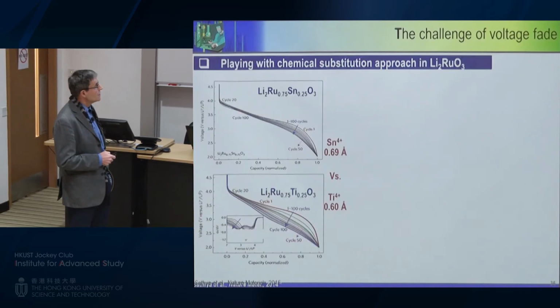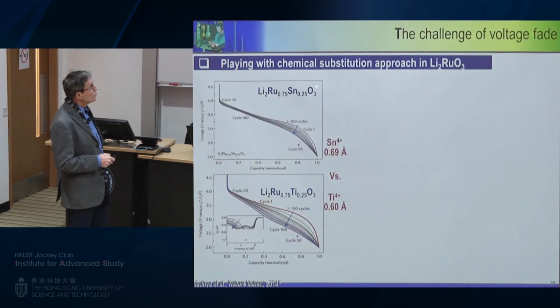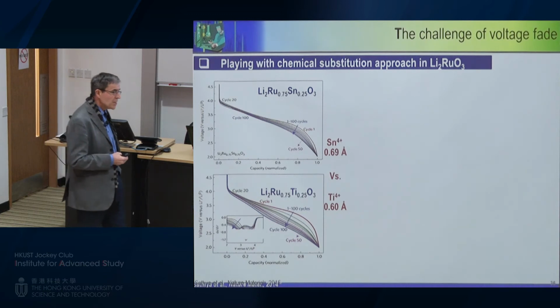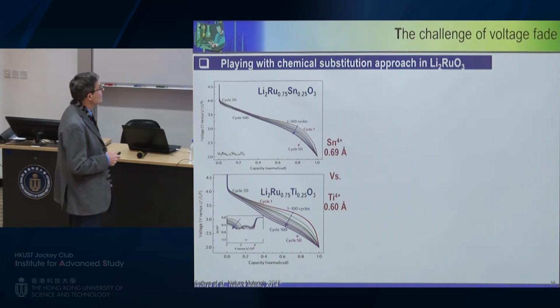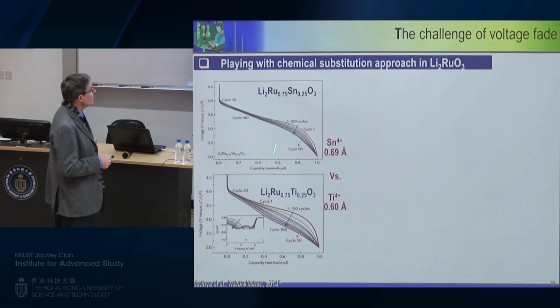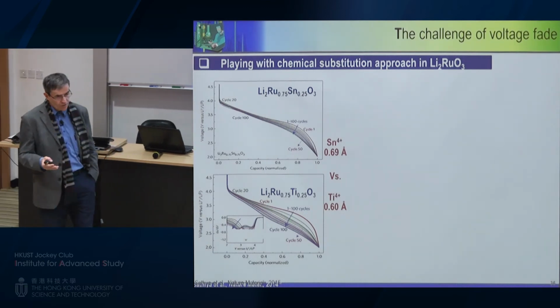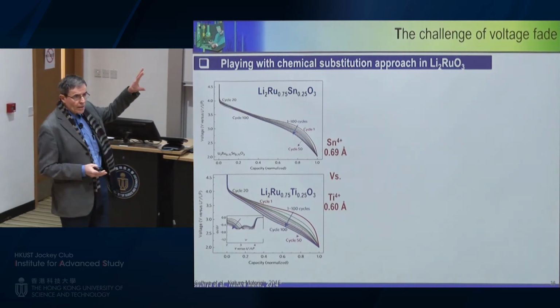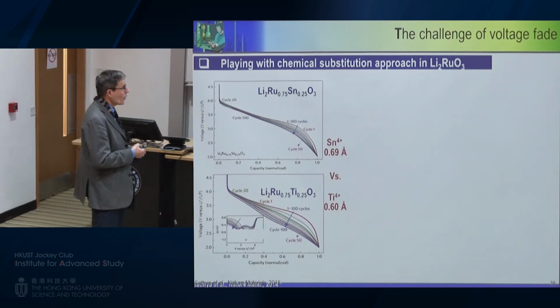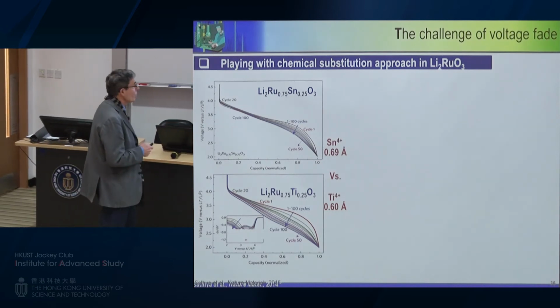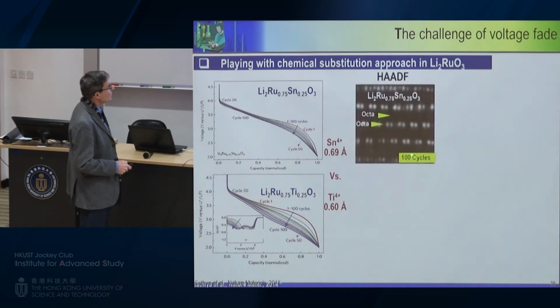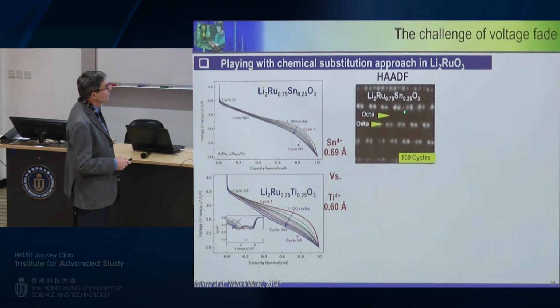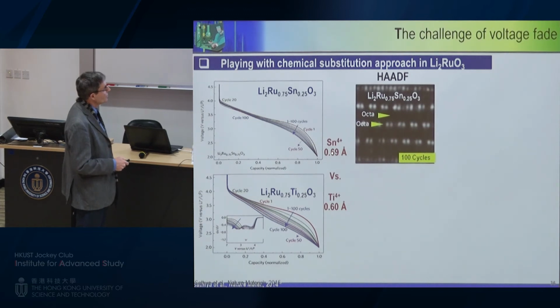The voltage fade, as I showed you, we are able to mitigate by using this kind of substitution, ruthenium by tin. And indeed, we have two samples here. When you replace by tin, we have limited voltage fade. When we have titanium, we have a huge voltage fade. And again, we have two types of systems to really understand the origin of this voltage fade. And when you look at this by microscopy, you can see that after 100 cycles, lithium ruthenium tin, everything remains clean in the discharged state.